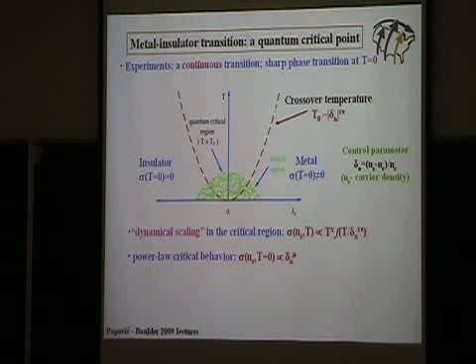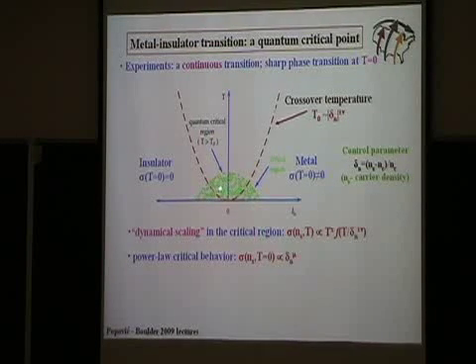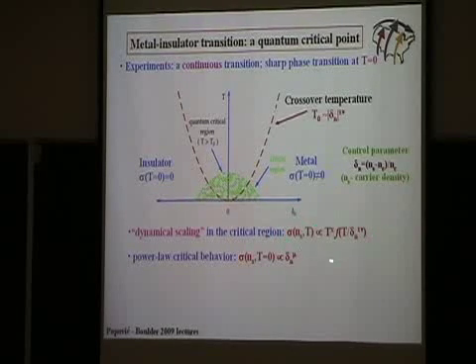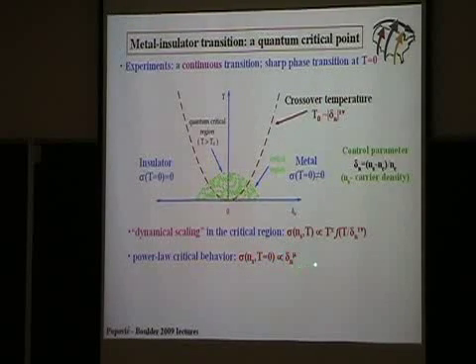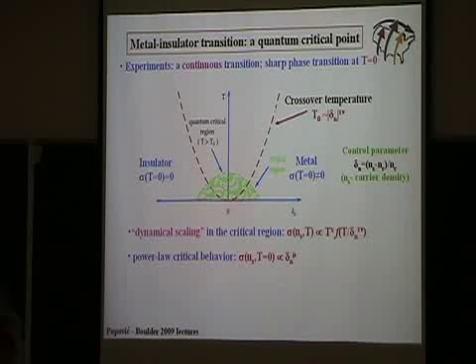So this is the experiment here shown. As I said, this is a continuous, second order phase transition. So close enough to this critical point, because the correlation length diverges, you expect that the microscopic details are no longer important. So you expect to see scaling of conductivity. In other words, for different temperatures and densities, the behavior of conductivity is described essentially by the same function. And this is what the experiments show, that in the zero temperature limit, the conductivity also decreases in a power law fashion. So in general, we expect power law behaviors.